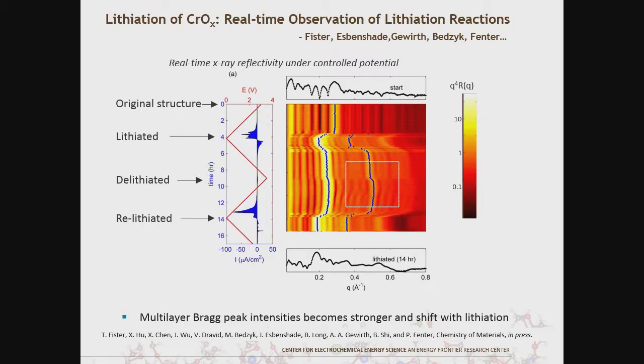All of a sudden you see a change in this peak position. If you think of this as a Bragg peak, the shift to smaller angles means it's expanding, as you might expect for this sort of reaction. Then when we go back up, it goes back up, but you can see the reaction is partly irreversible—it doesn't quite return to the same position, which is very typical of these conversion reactions.